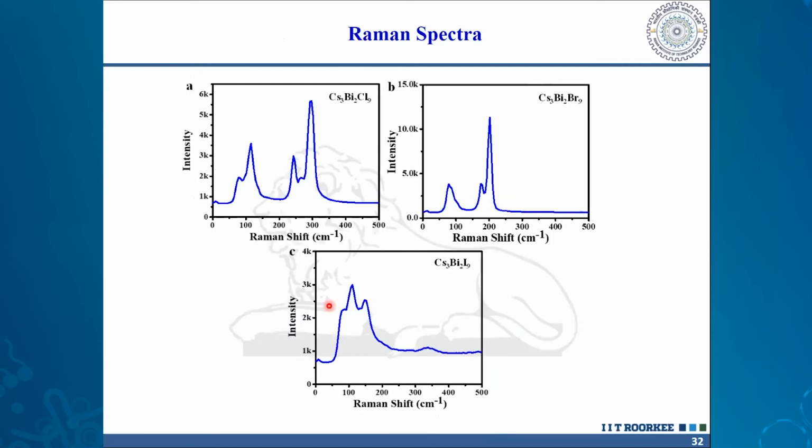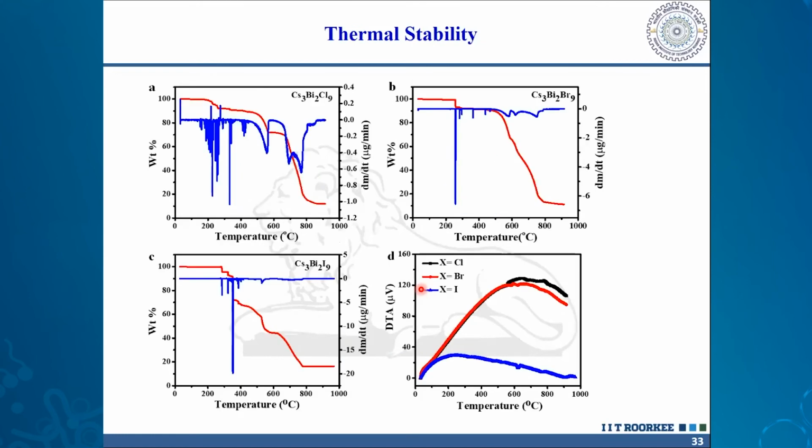And we have also taken the Raman properties to see whether they are vibrationally active, and the Raman mode analysis shows that all of these three materials are quite vibrationally active. So this leads us to think that if all these materials show good vibrational properties, and since bismuth is there, it will probably show a very strong electron-phonon coupling. And if there is a strong electron-phonon coupling, one can probe it by some kind of spin properties, by EPR spectroscopy, and it might be suitable for spin-based devices.